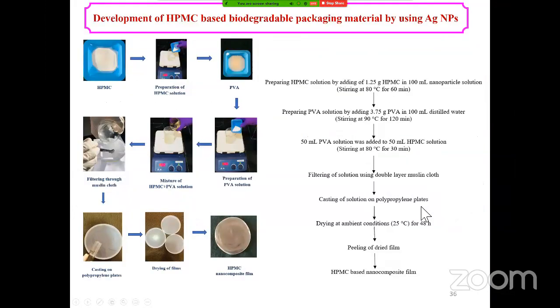And coming to the development of HPMC, hydroxypropyl methyl cellulose, it is a part of my PhD research, and I've developed biodegradable packaging material using silver nanoparticles. I have taken HPMC and prepared the solution, and PVA I've prepared the solution. The mixture, 50% of both the components, I filtered through a muslin cloth, and it was cast on polypropylene plates and dried for about 48 hours. We get the HPMC nanocomposite film.